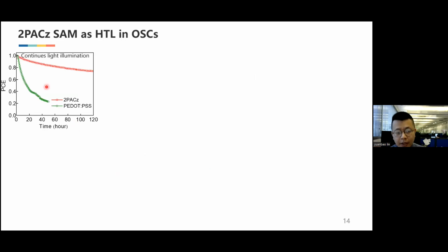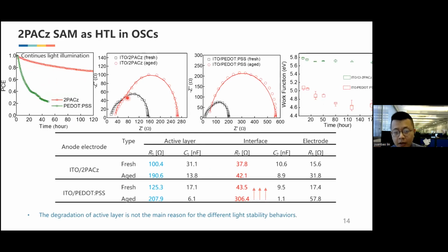Also for the stability, these 2PACz have a higher stability as compared to the PEDOT:PSS. This is because we use EIS to detect the fresh device and the aged device. The interface resistance of the SAM-based device is more stable as compared to the PEDOT:PSS. This should be because PEDOT:PSS is an acidic material, so it will cause degradation of the ITO during the aging test. We also checked the work function of the ITO/2PACz, ITO/SAM, and ITO/PSS. The ITO/SAM is more stable than the ITO/PSS.